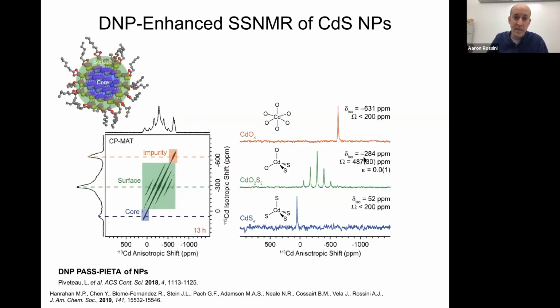Now, there were a lot of spinning sidebands, and it was difficult to interpret that spectrum. So we then do a sideband separation experiment, in this case, a magic angle turning experiment. Lindén's group has also done these types of experiments with PASS-PIETA. What this experiment gives us is an isotropic spectrum in the indirect dimension. And then we can pull out rows that will show us the anisotropic sideband manifold for those different isotropic chemical shifts.